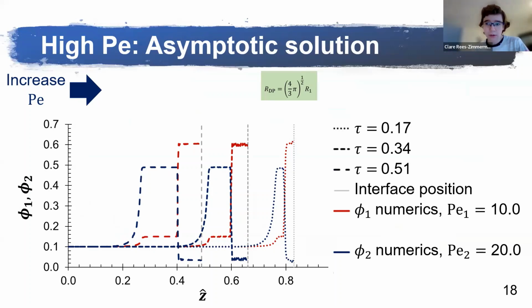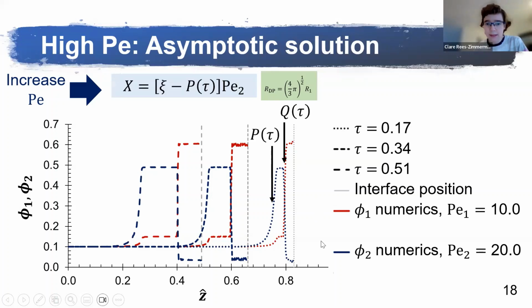You'll also note that it starts to look like these concentration profiles are attaining a constant shape moving across the film over time. This is the inspiration for deriving an asymptotic solution. I did this by noting that there are two key transitions in the profile, which I've labeled here as P and Q. P is the diffusion-evaporation front, and Q is a kind of diffusion-diffusiophoresis front.